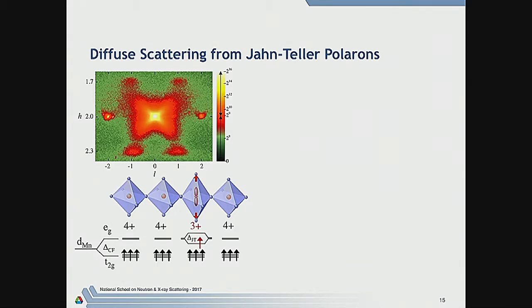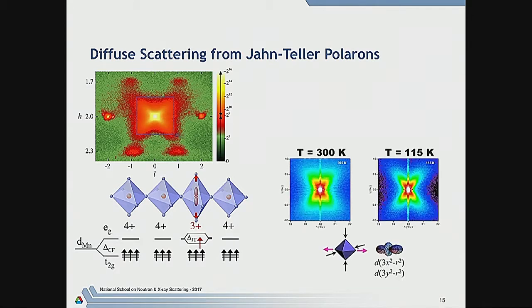In these materials, at higher temperature in the paramagnetic phase, this kind of what we'd call a small polaron actually gets frozen. In other words, the electrons get trapped on these sites. And so you get a lot of disorder on the lattice caused by the fact that some of these ions are Jahn-Teller distorted and some are not. Okay, at low temperature, they all become homogeneous again. And so you can tell something about that just from what we call Huang scattering, which is scattering around the Bragg peaks, which can be modeled in terms of the strain field that arises around one of these polarons.